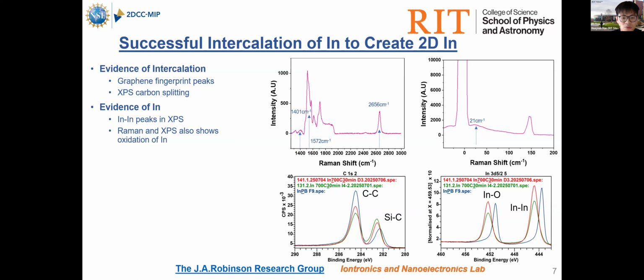As I mentioned earlier, since we're using a defective buffer sample, that means this monolayer graphene might not fully protect our intercalated atoms from oxidizing, and therefore it might just be covering all the pristine indium signal. However, we can still confirm we do have some indium that is intercalated from the XPS.